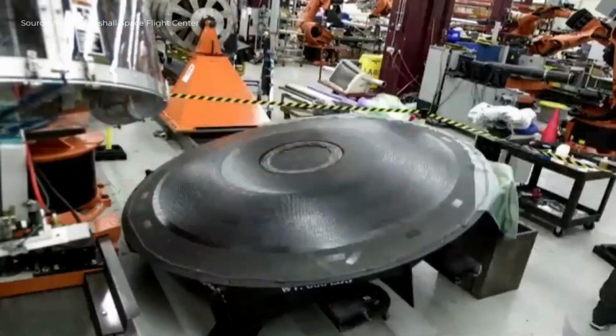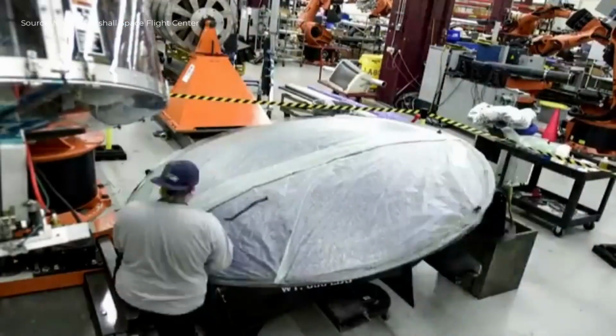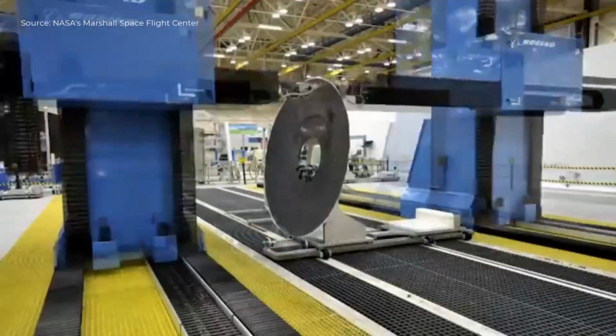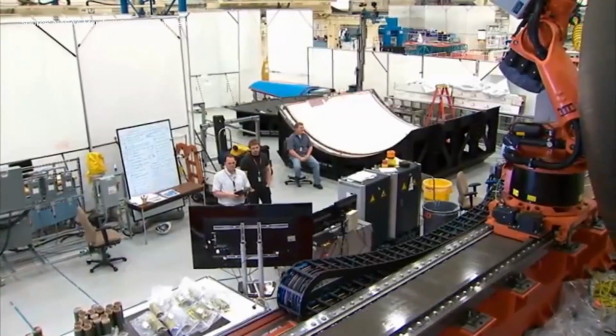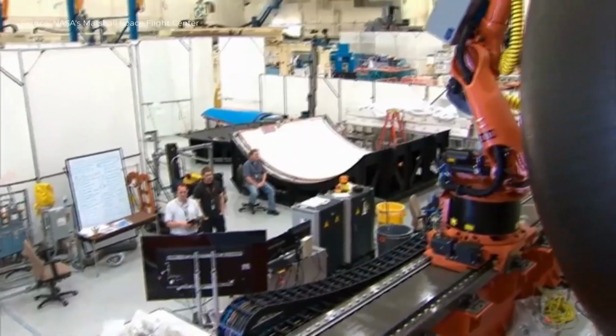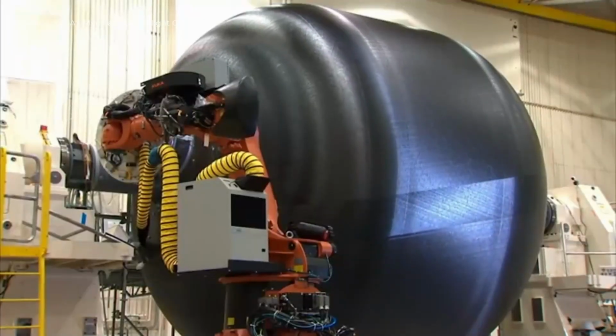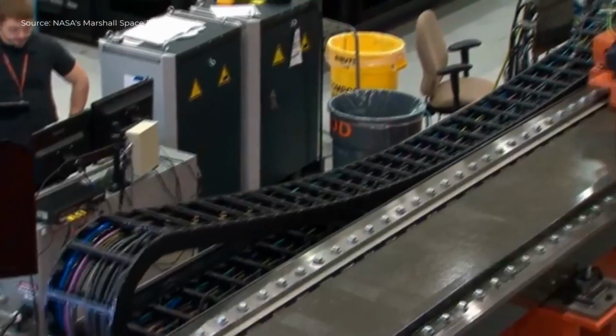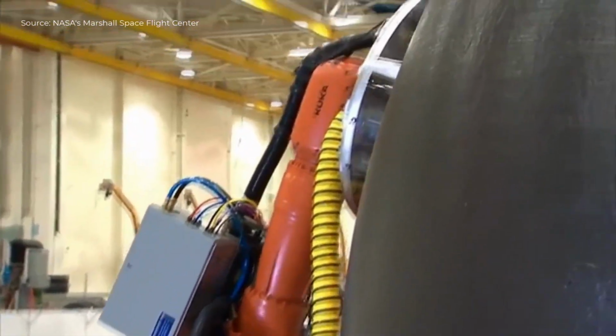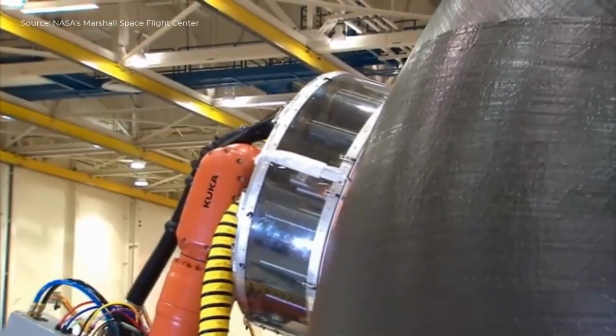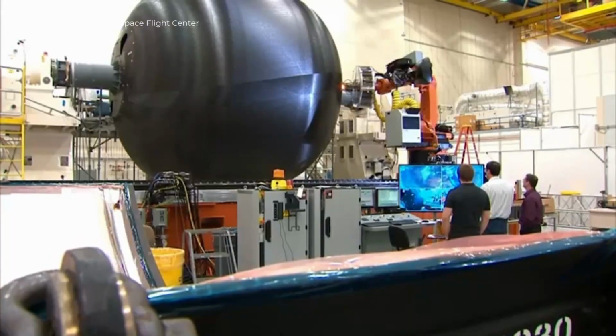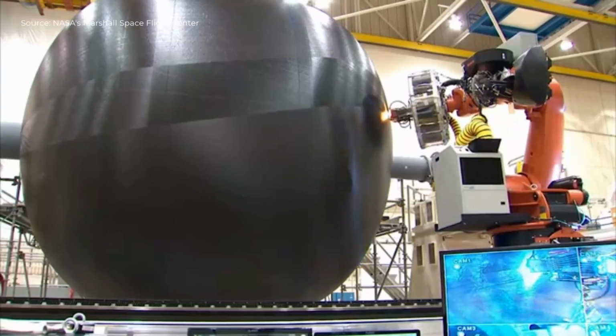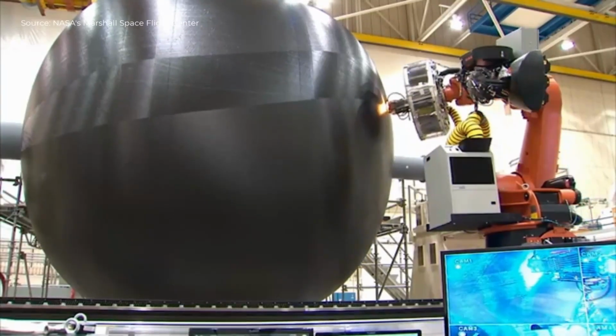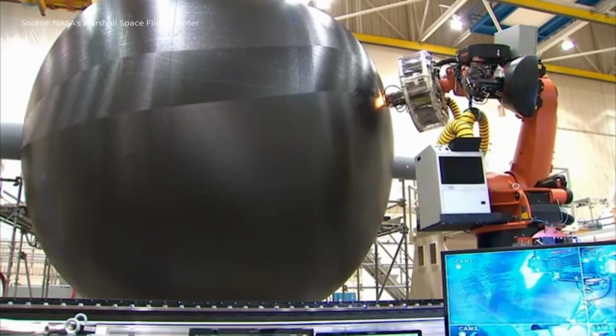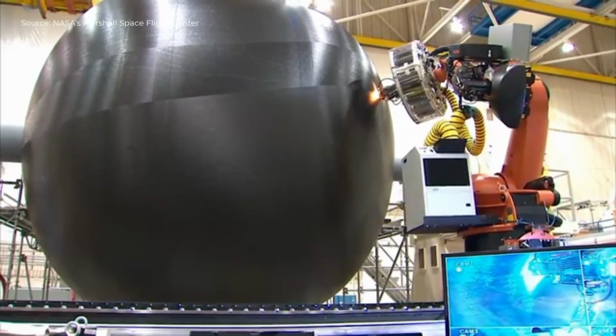Engineers first designed the composite rocket fuel tank using advanced modeling techniques. The manufacturing process began with automated fiber placement, where resin-impregnated carbon fibers were precisely laid onto a large mandrel to form the tank structure. This technique minimized material waste and improved strength. Instead of traditional autoclave curing, the team used out-of-autoclave methods, significantly reducing cost and complexity.